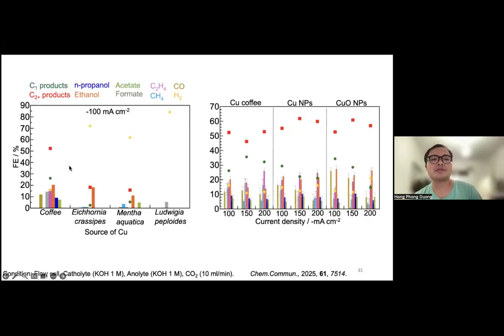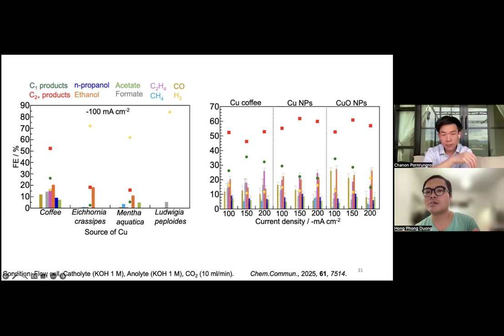She found this, and then she gave the sample to us, and we tried. This is very interesting: the coffee powder sample gave a very good efficiency for C2+ products from CO2 reduction. In this case, we only tried CO2 reduction because this is very original and elementary research. So we just tried CO2 reduction instead of CO. We might try CO reduction later. Coffee powder was the best one among the plants. When we compare even this coffee powder with the commercial catalyst, the nanoparticles of copper or copper oxide, it shows an almost very comparable result.